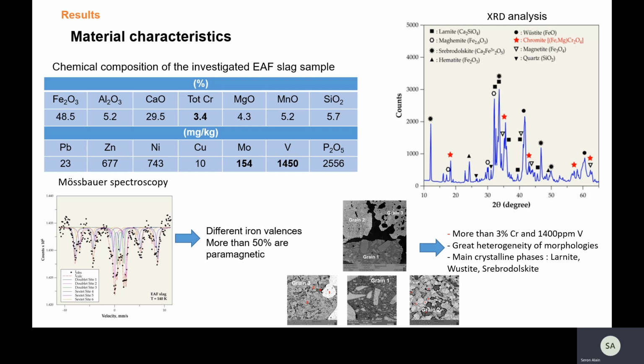Before performing thermal treatment and hydrometallurgical steps, the slag material was first characterized in order to know its chemistry and its chemical reactivity. Here is the chemical composition of the slag sample obtained by X-ray fluorescence analysis. The main elements are iron and calcium, and then silicon, aluminum, and manganese. But it is important to note that chromium content is 3.4%, vanadium content is close to 1,500 ppm, while molybdenum content is more than 150 ppm. Such amounts justify the interest in these slags.